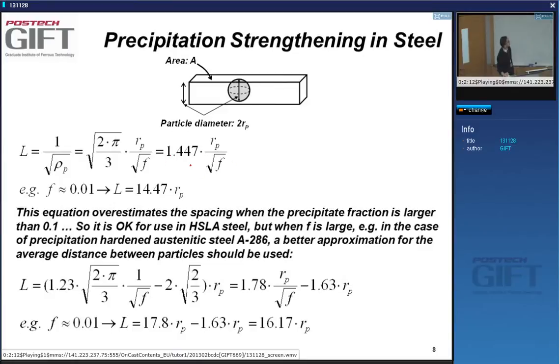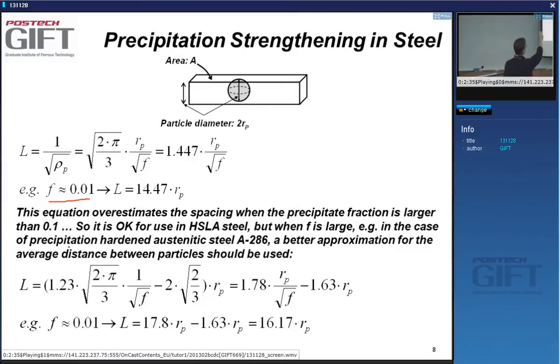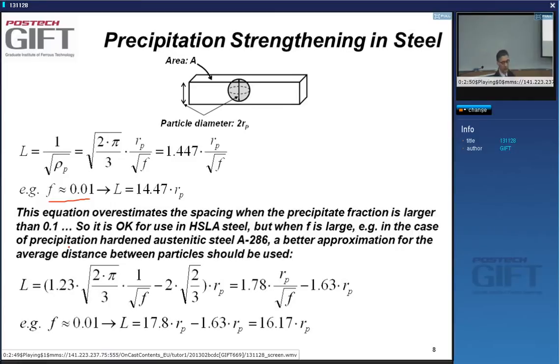Here is an example. If you use a volume fraction of 10 to the minus 2 — by the way, this is volume fraction, so the maximum value is 1, not 100. So F = 0.01 is 1%. That means L will be 14 times the particle radius. This is the basic equation. You can use it if you have low volume fractions.